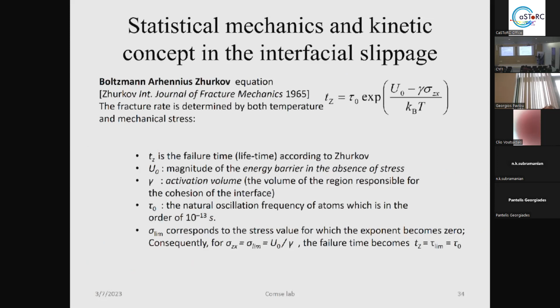The second thing that attracted us on this problem is to calculate the time of the failure, from the prism of statistical mechanics and kinetics. The first who did that was Zhurkov in 1965, who took an activation energy equation of Boltzmann-Arrhenius that you can see here, and he inserted the activation volume gamma, which depicts the space of the interface where the failure will happen, and the shear stress that he put on the system, and he was able to calculate the time of failure of the system.